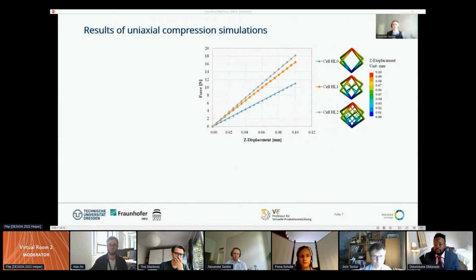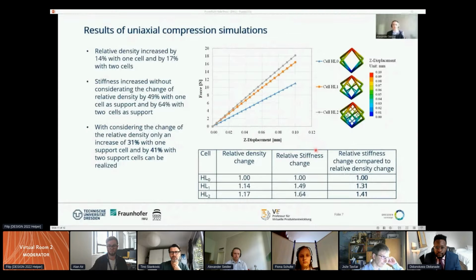The required force for the deformation of each cell design is shown in the chart, and based on these, the compression stiffness was calculated. So, all in all, comparing the result of all self-similar cell designs with the base cell, the stiffness increased by 49% by inserting one subcell and by 64% inserting another cell. However, the relative density also increased with respect to the base cell by 14% inserting one subcell and by 17% inserting another cell. Therefore, considering the light-weight aspect, the change in the stiffness is put in relation to the change in relative density. So the resulting change in relative stiffness in relation to the base cell has increased by 31% by inserting one subcell and by 41% inserting another subcell.